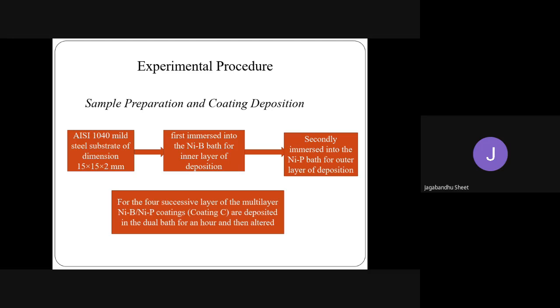Firstly we prepare the samples by grinding them several times. We also first clean the rust from these samples by dipping them for 1 minute in a 50% hydrochloric acid solution. After completion of the sample preparation, the samples are submerged in the previously prepared nickel-boron bath solutions.